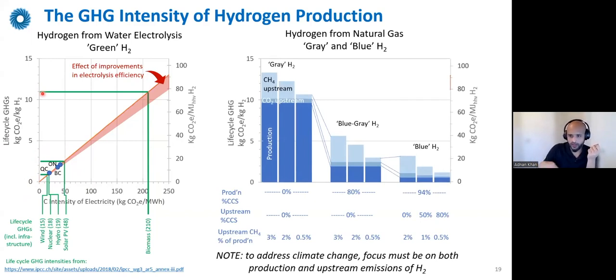The graph I have here, again, is a very busy chart, but I'll try and break it up for you. It's the life cycle GHG intensity of your hydrogen, in kilograms of CO2 per kg of hydrogen, as a function of two different things. In the chart, carbon capture rates are 0%, 80%, and 94%. So 0% basically means gray hydrogen, and the other percentages are carbon capture rates that are possible today. But I also have upstream methane emissions: at methane leakage rates of 3% all the way to 0.5%, I have plotted the GHG intensity.